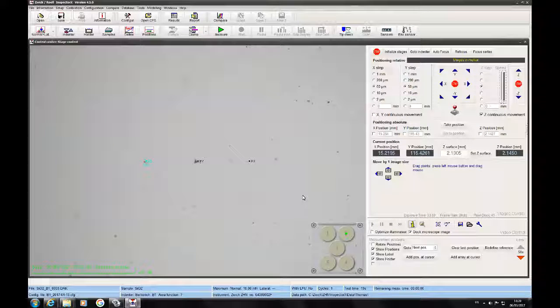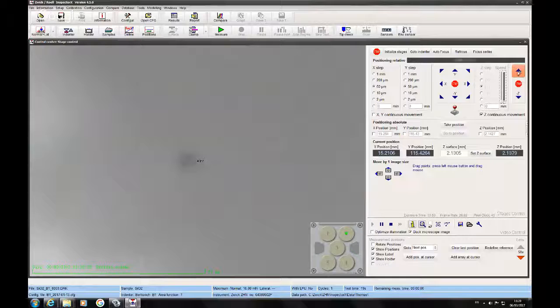And we can now switch to a higher magnification. We have to correct the focus level. Now the illumination is a little bit influenced by the light in the room. See now, you see the indent. And we can also measure it, it's quite small, about 4 micron. If we go to the next position, we see here, possibly or not, a very small indent of the 10 millinewton. This is demonstrating the resolution of the optics. We can even double the size. Here, this is a size of less than 1 micron that you can even resolve in the optics.